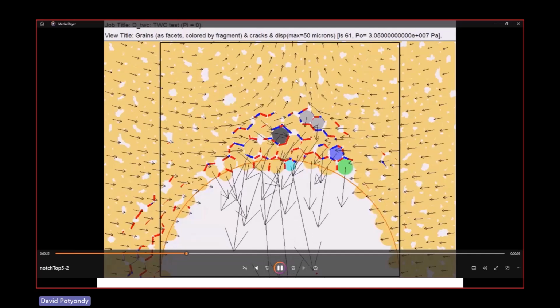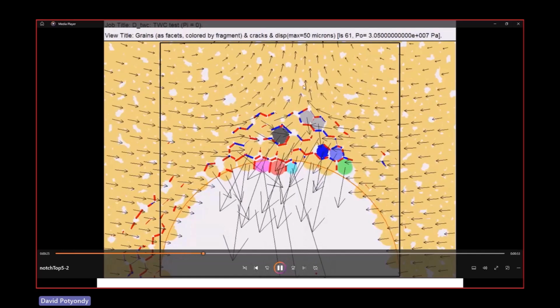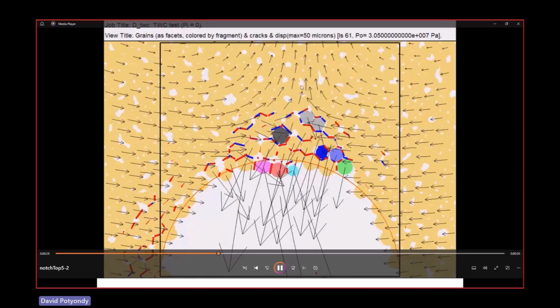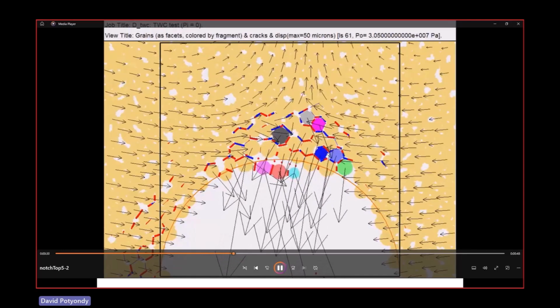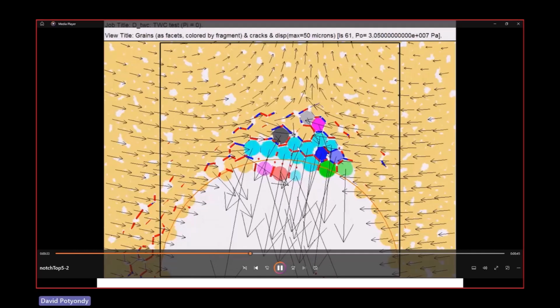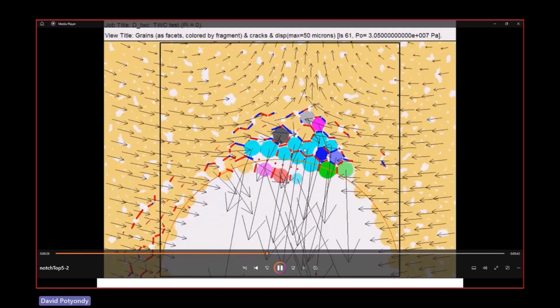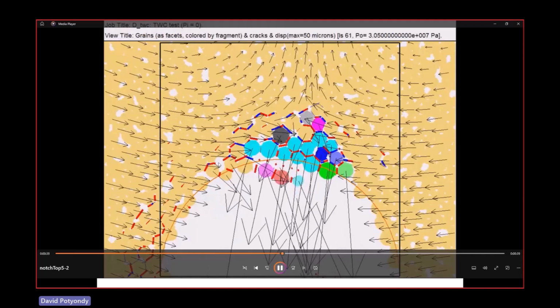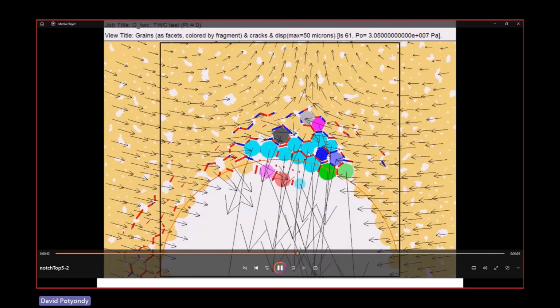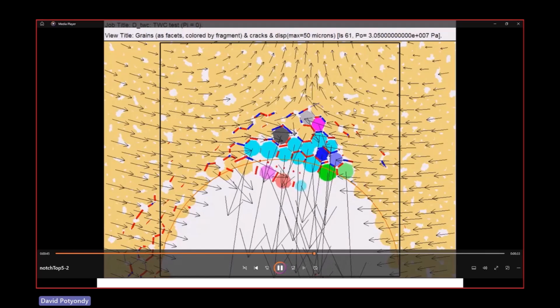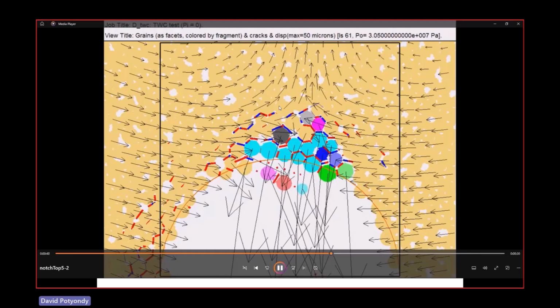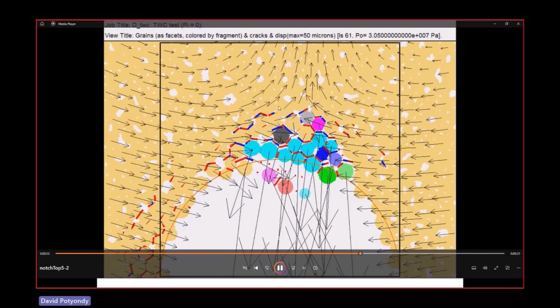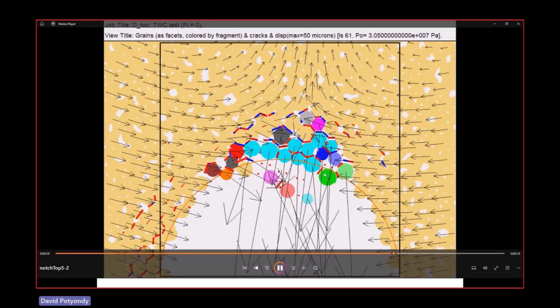You form a very high compressive region up here, and that's what stops the damage from forming. You can see the big dilation, and these regions here are the fragments that are forming. You're getting these surface-parallel fragments. This, by the way, is a super crude model with very large particles. We of course ran particle systems with much smaller particles and got the same type of response at a much higher and better resolution. I can show you that in that talk if you're interested. But this is a good illustration of the behavior.